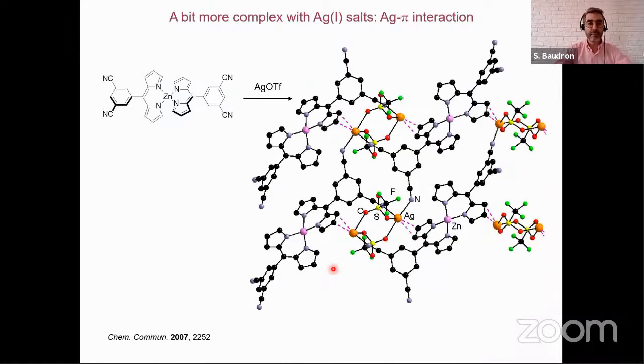One of the first results we obtained was to use the zinc complex bearing nitrile groups at the periphery, and we assembled it with a whole variety of silver salts. We obtained crystalline material, and this is the crystal structure of such a heterometallic system, where you have here in orange the silver cation that is coordinated to the peripheral nitrile group of a dipyrrin ligand, a triflate anion, but the silver cation also tends to sit on top of a carbon-carbon double bond of a pyrrole system with a distance of 2.4 to 2.6 angstroms. And this type of organization is actually suggestive of silver-pi interaction.